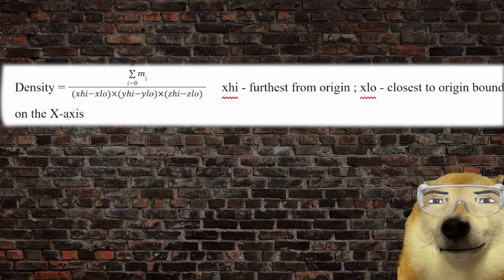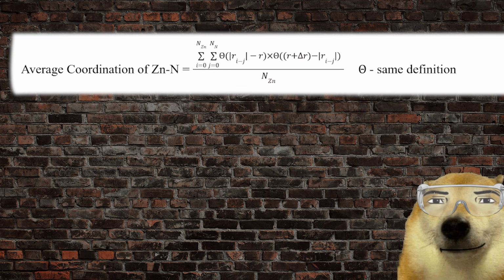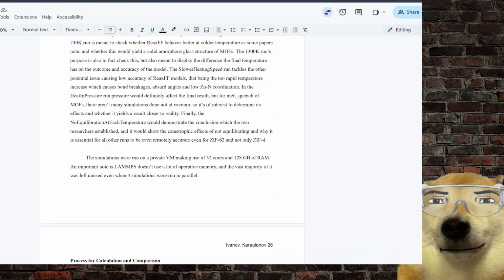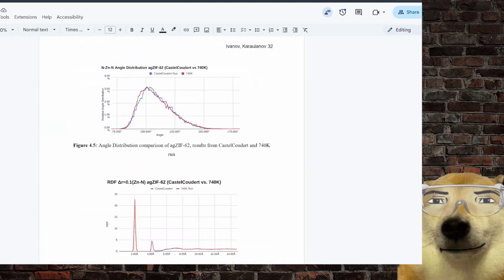Their envelope density was also checked. We looked for values closest to reported from experimental trials. And finally, coordination of zinc-nitrogen with a cutoff at 2.3 angstroms, where we try to retain the greatest possible coordination, as in theory the best glass should have very high coordination in order for the ZIF to not lose its chemical properties.